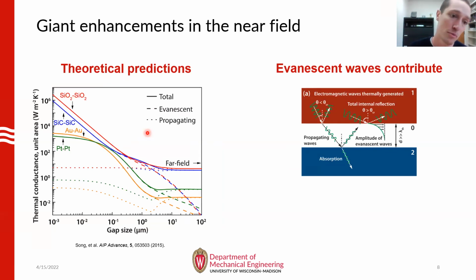And this is illustrated in the plot on the left, where the computed radiative thermal conductance between two planar surfaces is plotted as a function of the gap size. This was done for various materials comprising the two surfaces. As you can see, at room temperature, as the gap size is reduced below around 10 microns, you start to see these large enhancements in the conductance, which depends a lot on the specific materials involved.